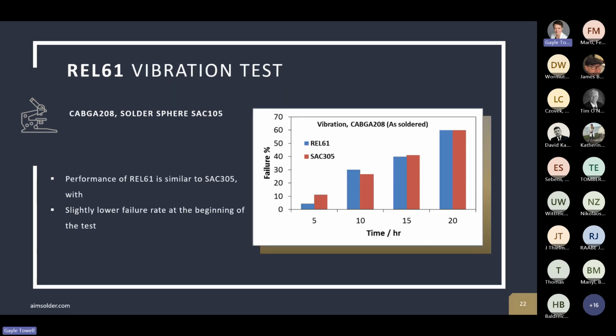This was a vibration test, so shake it and see if you break it. And what we see in this particular test is the performance at the end of the test is somewhat similar between the 2 alloys, with slightly lower failure rates with the REL61 in the beginning. So here the performance is more comparable, but with lower failures in the beginning for REL61.